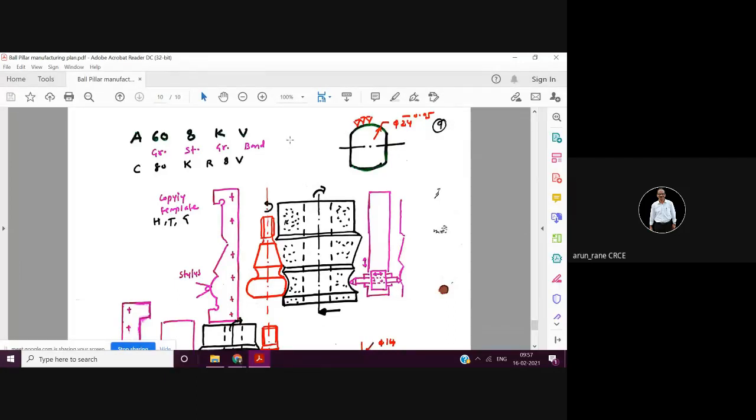So in this case, as a process engineer, you have to suggest that this long component has to be held vertically. So when you're holding it vertically, this shaft, then what happens? Your center of gravity is in the vertical axis down, isn't it? So the entire weight is acting in the y-axis direction. So there will be elongation of the component, but the component will not bend. There may be a slight bend, but it will not get bent the way it would if you keep it in a horizontal condition and do the hardening.